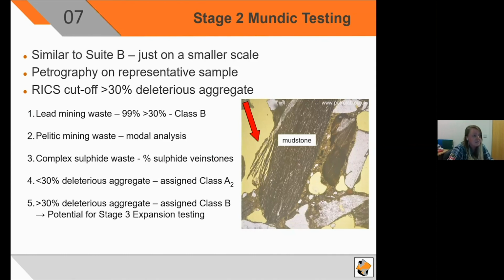We've also got pelitic mining waste, which needs a bit more assessment of modal analysis and point counting. We've got complex sulfide waste, which is based off percentage of sulfides rather than pelite aggregate. But at this stage, from the stage 2, if you have less than 30% deleterious aggregate, it is assigned Class A2, and that means it is fit for mortgageable purposes. However, anything greater than 30% deleterious aggregate is assigned Class B, and then becomes unmortgageable.